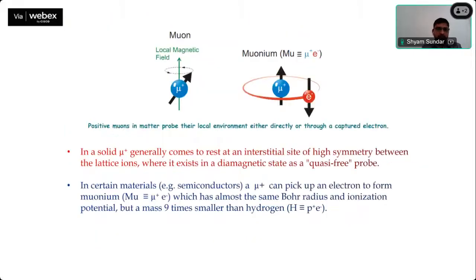Another field with the muon is called muonium physics. As you know, in a general experiment in metals, we put a muon into the system, and it starts precessing around the local magnetic field, and we see a positron. But if your system has low electron densities, for example semiconductors or some insulators, then what happens when your muon goes into the system? It captures an electron, and then it resembles a situation like a proton, where you have a nucleus and only one electron. So it's some sort of hydrogen-like situation.